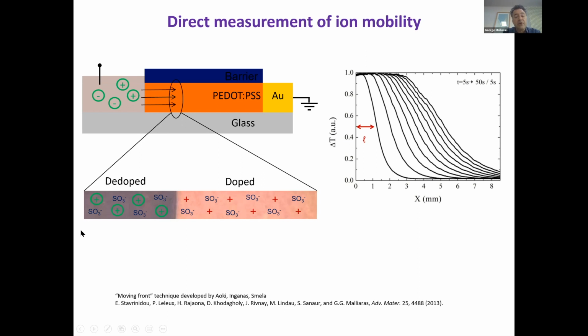And as it does, it changes the color of the material. So if you just shine light through this sample, you can see a de-doping front spread through the sample. There is a lot of information here. For example, the fact that the plateau here, the top, stays at the same value means that the compensation is complete, and the number of cations that you inject compensates completely the sulfonates throughout the material. It also means that there's no injection barrier for ions, but ions can penetrate the film very quickly, very easily.